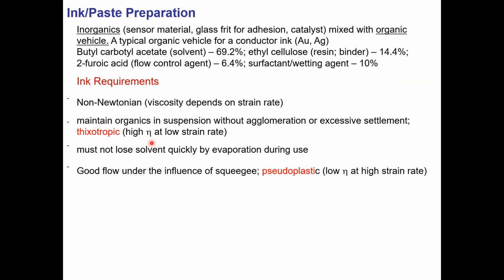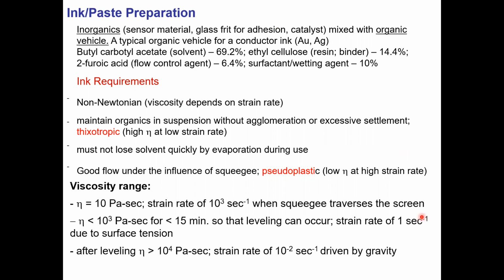during settlement, so it should be high viscosity at low strain rate. Also, it should be pseudoplastic, meaning it should decrease in viscosity at high strain rate. And this is particularly during the flow or squeegee operation on the screen. So in terms of viscosity ranges, you want viscosity roughly to be of the order of tens of pascal seconds at a straining rate of 1,000 per second. And this is typically the strain rate when the squeegee is traversing on the screen.